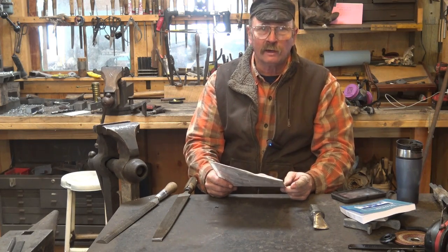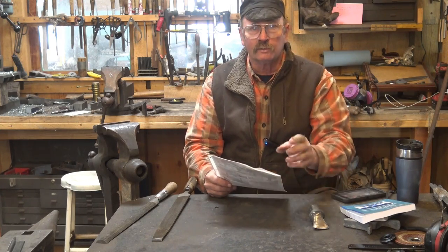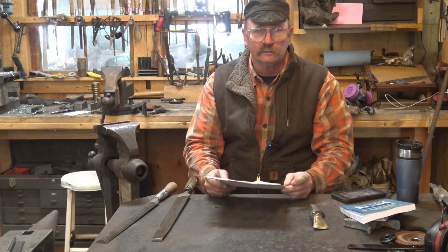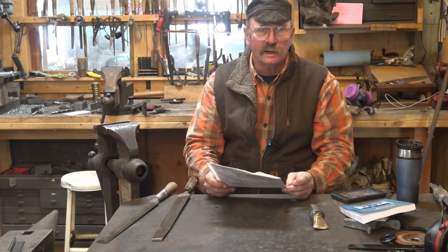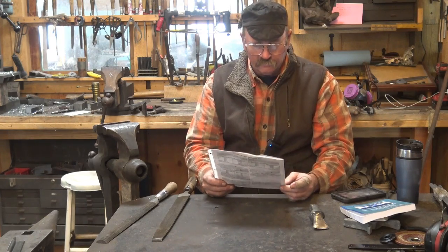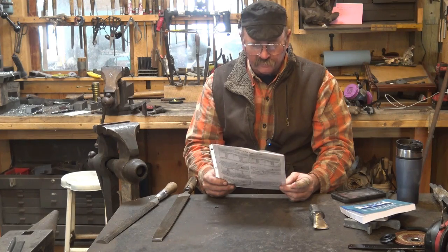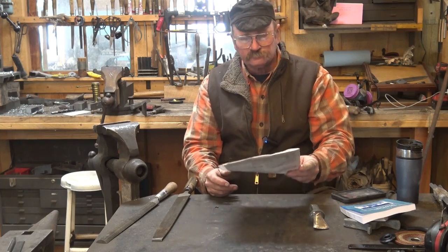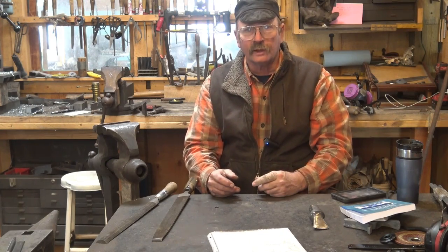And you could probably get by with quenching it in oil. It would not be very hard at all. But for a hardy, it would probably survive just fine because you're only using it on hot steel. And you're going to take all the temper out of it eventually with hot steel anyway. And then it has a tempering guide. We can bring it to a Rockwell of 56 if we temper it at 400 degrees, and that's probably about right. So that's a good resource to have right there.